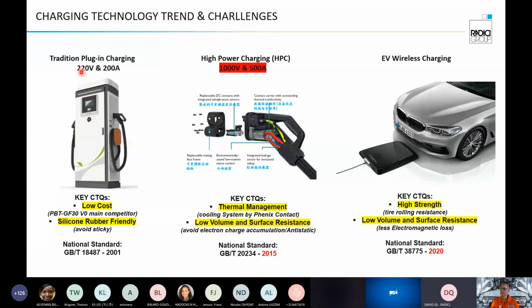But nowadays, as you can see here, in 2015, the China government launched new national standards to use high power charging systems, which use 1000 volts and also 500 amperes. This is a quick charging system, but with this high voltage, you need to pay attention to the resistance of both volume and surface of the materials to avoid electron charge accumulation that brings up static problems.